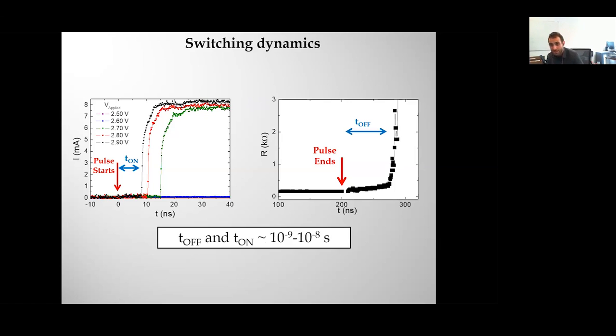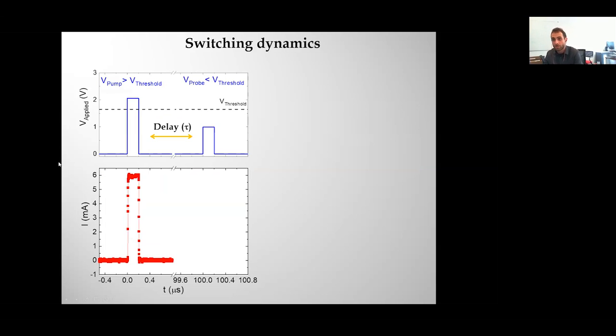So what this means is that as long as you have pulses that are farther apart than a few tens of nanoseconds, they should be non-interactive, because that's the characteristic time scale of the relaxation and of how fast it goes into the metallic state. To check that, we did the following experiment. We sent a voltage pulse that is above the threshold. This is voltage as a function of time, and this is current as a function of time. So we send one pulse above the threshold, and it induces the transition.